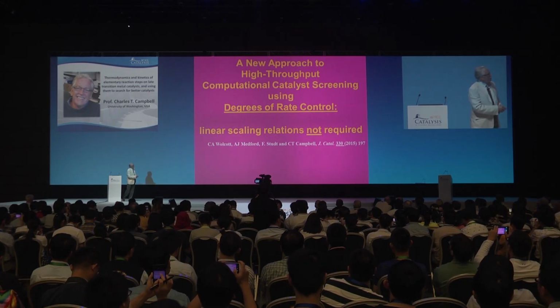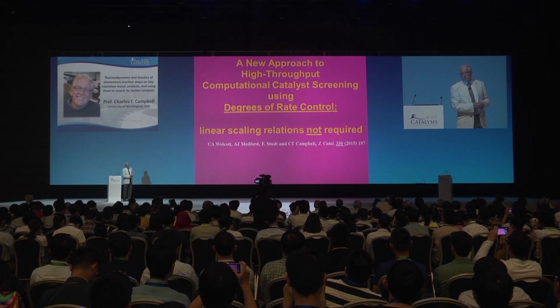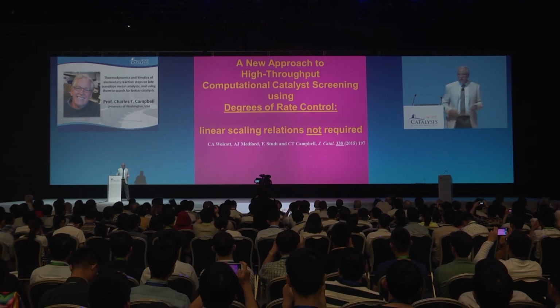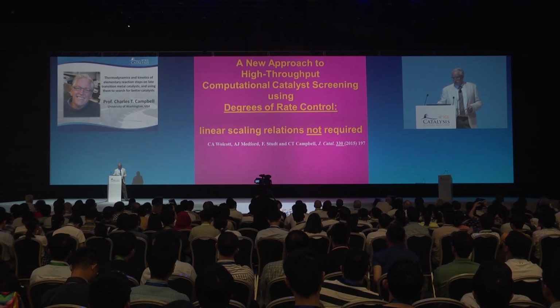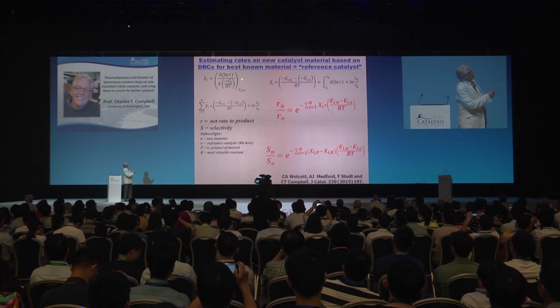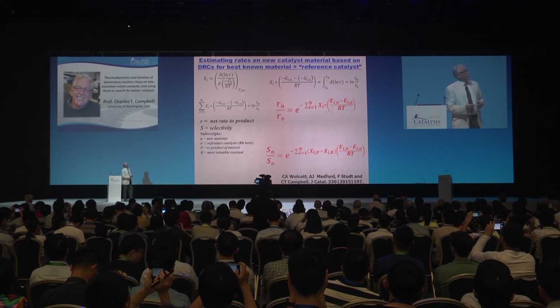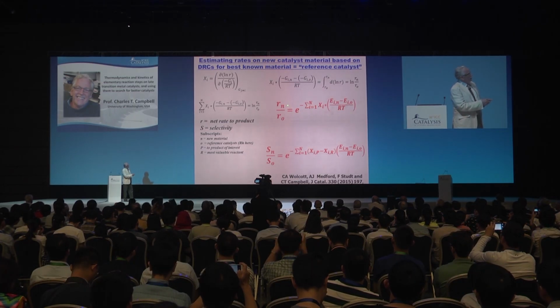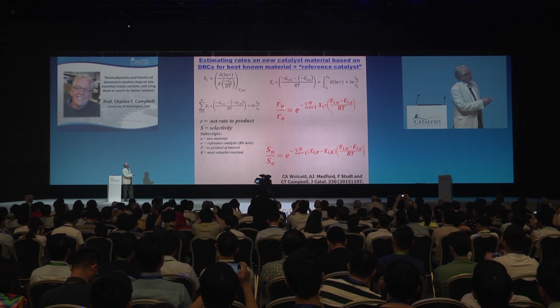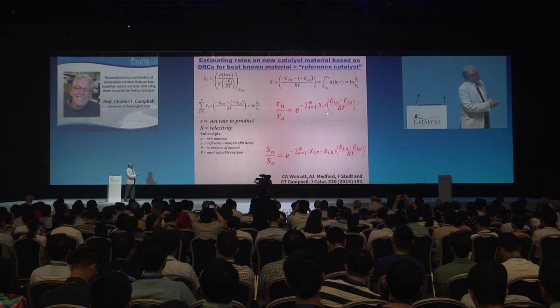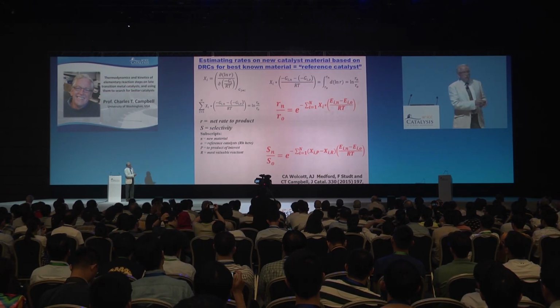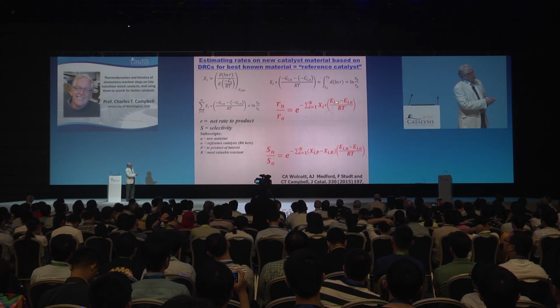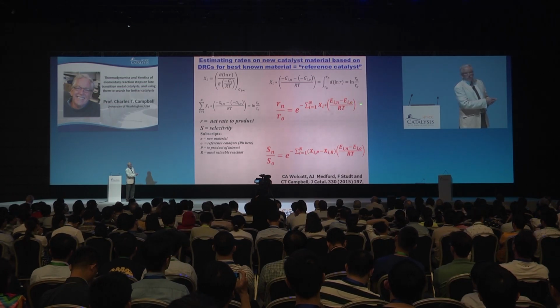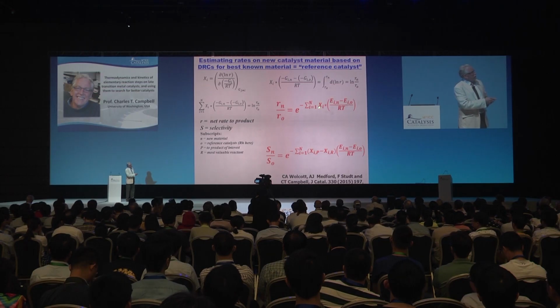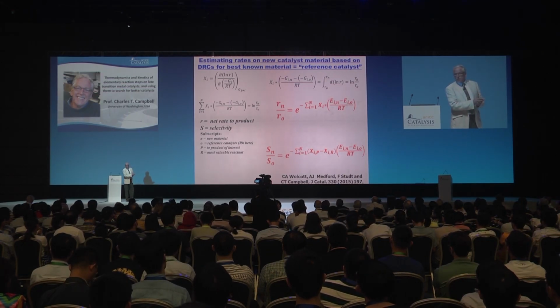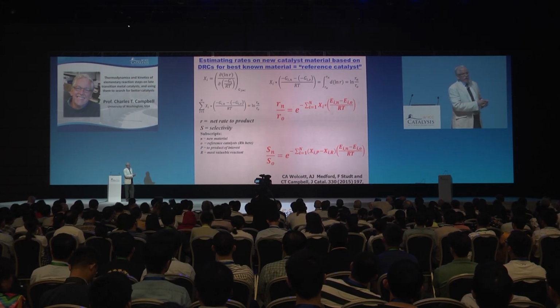We've recently described a new way for doing such computational searches for better catalysts based on density functional theory that doesn't require the linear scaling relations, which is an approximation in his approach. And without belaboring the math, we take the definition of the degree of rate control, we integrate that, and we can then computationally predict the rate of the reaction on a new material relative to the rate on a reference material based on only the DFT energy differences between the energy of the species involved in the mechanism on the new material relative to that on the reference material, and the degrees of rate control for those species on the reference material, summed over all species in the reaction, transition states, and intermediates.